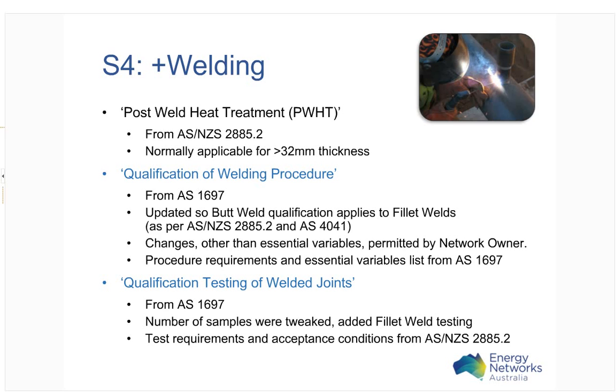The qualification testing of welded joints has also been taken from AS1697. The number of samples in this table was tweaked a little bit, with the addition that if you wish to qualify only a fillet weld rather than a butt weld, that's also applicable to fillet welding. The test requirements and acceptance conditions have been taken from AS2885.2 and still apply, so it shouldn't be too much of a shock to anyone there.